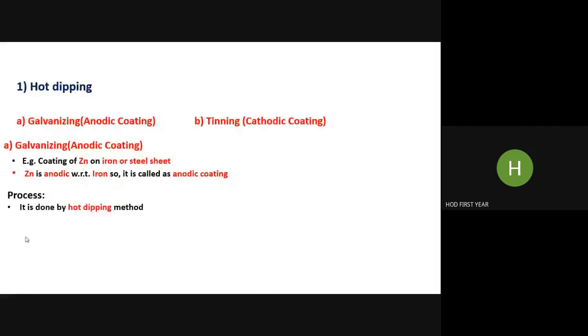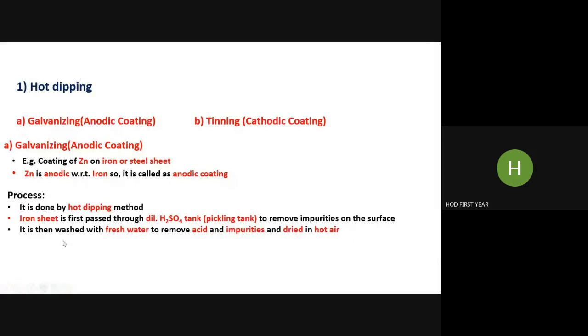So process, it is done by hot dipping method. Here we consider the example of iron sheet and we will apply zinc coating. So first, under preparation of surface, is acid treatment, sulfuric acid treatment. That sheet is first passed through dilute H2SO4 tank. That tank is called a pickling tank, or pickling process, to remove impurities on the surface. It is then washed with fresh water to remove acid and impurities and dried in hot air. So now the cleaning process is finished. First step is cleaning.